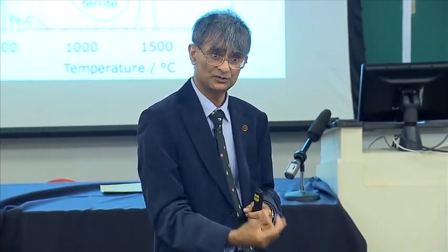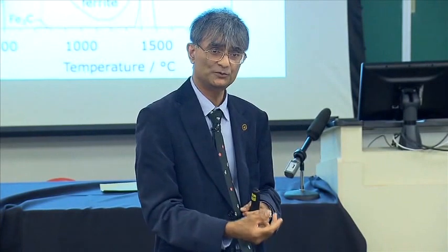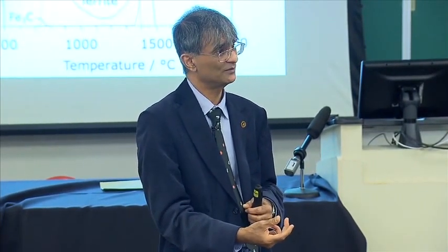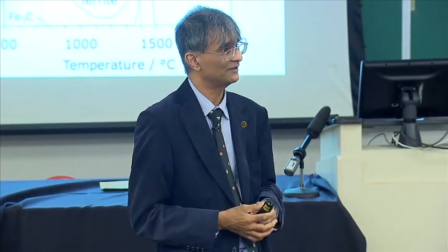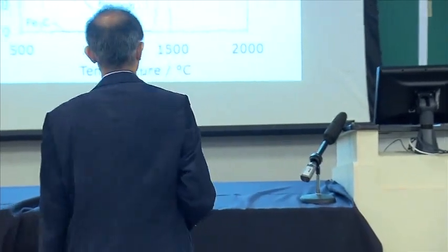So when you spot weld, you have very rapid heating and very rapid cooling. So if you have a high carbon concentration, you get brittle martensite forming. But if you cannot form 100% austenite, you cannot form 100% martensite. That has to be good for spot welding.